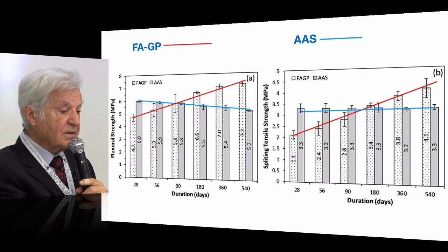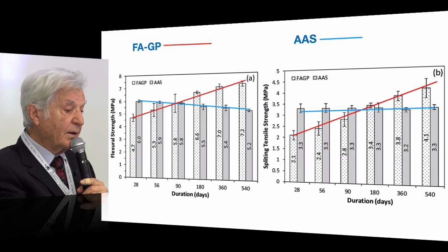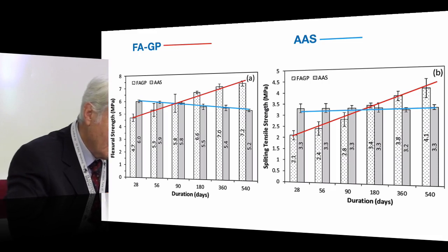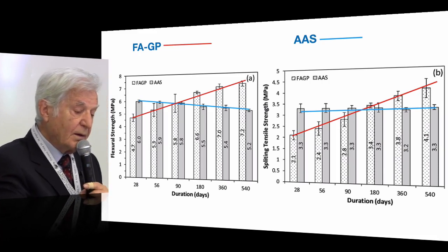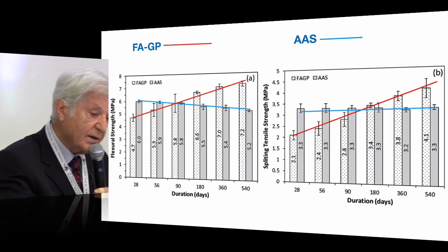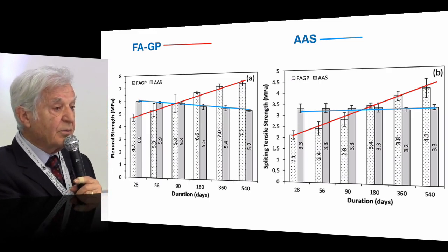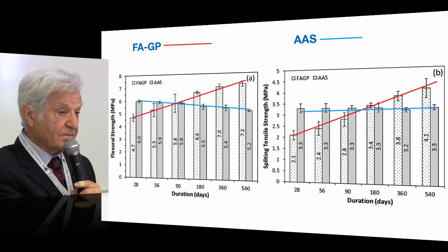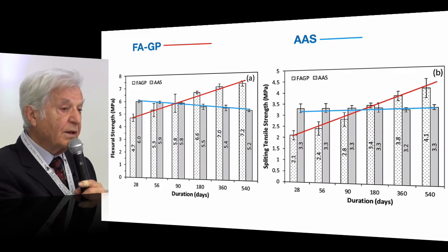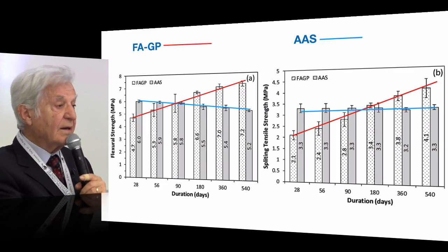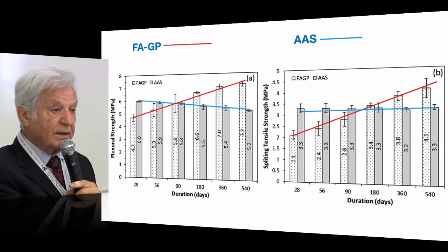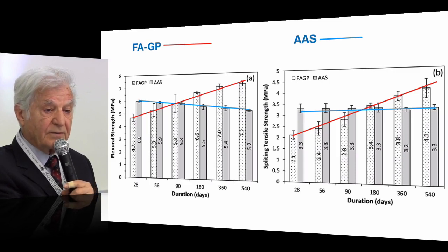I show the results. You have here in red the evolution of fly ash based geopolymer, in blue the evolution of alkali activated slag. On the left, flexural strength. For the alkali activated slag in blue, it diminishes, and for the fly ash based geopolymer, it increases. For splitting tensile strength, for the alkali activated slag, it remains constant, but for the fly ash based geopolymer, it increases. So even if at the beginning alkali activated slag has higher strength, long-term durability is not the main characteristic of alkali activated material.